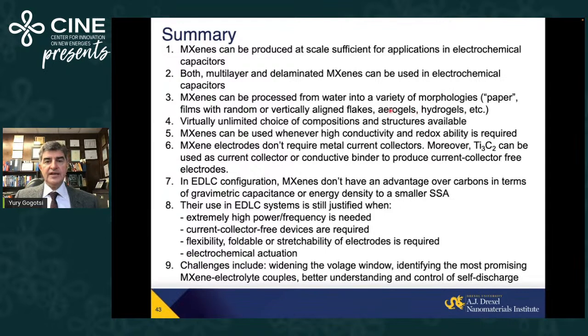But naturally, you can read papers on graphene oxide, and you can do exactly the same thing with it. Virtually unlimited choice of composition and structure means properties are tunable, ideally programmable. And whenever you think of a need for high conductivity and redoxability, those are MXenes, because they have higher conductivity than reduced graphene oxide, and they offer reversible redox of transition metal oxides, hydroxides.